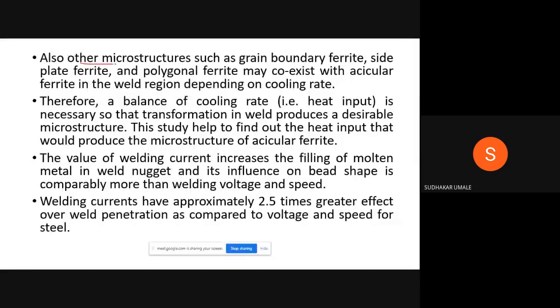So during this conversion from molten metal to the solid, during formation of this, what type of microstructures do I get? The major microstructure is acicular ferrite, which is desirable. Some boundary ferrite I get. Some side plate ferrite I get. Some polygonal ferrite I get. And the majority is acicular ferrite in the weld regions, and it depends on the cooling rates. So this is the first condition.